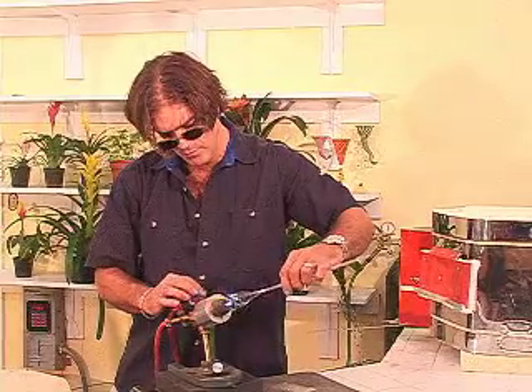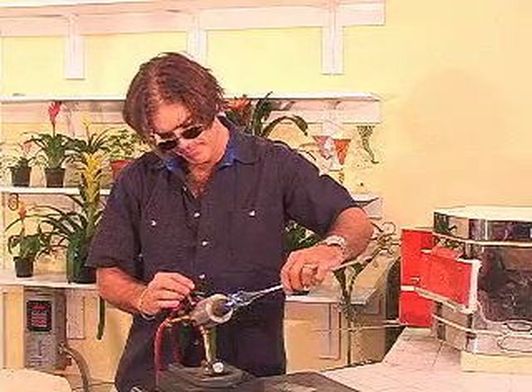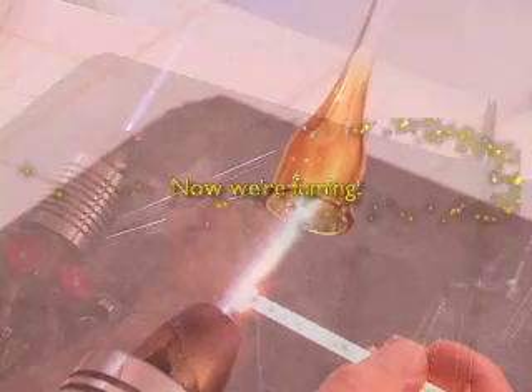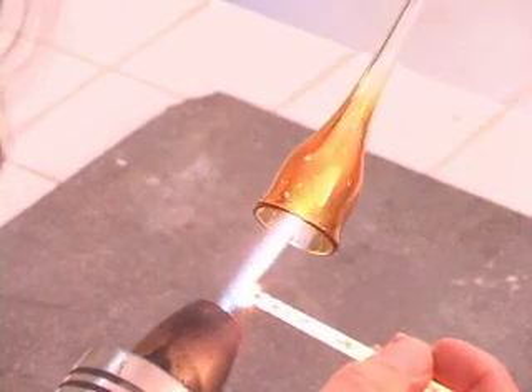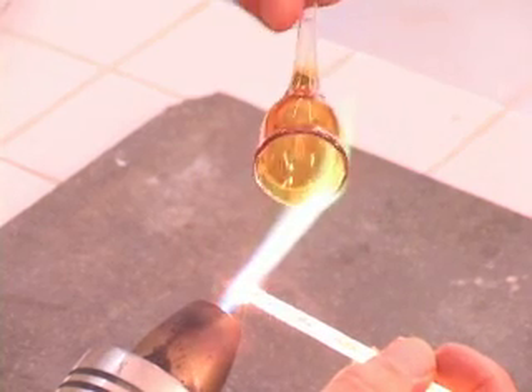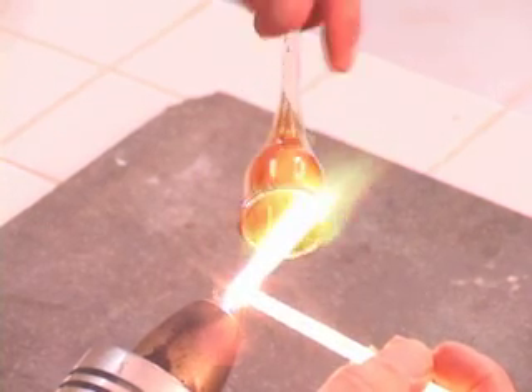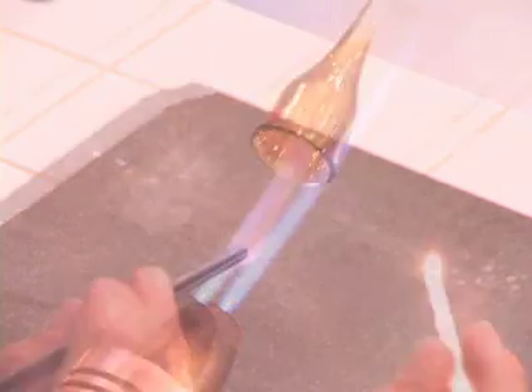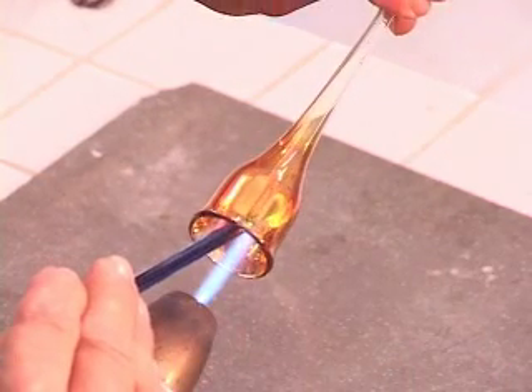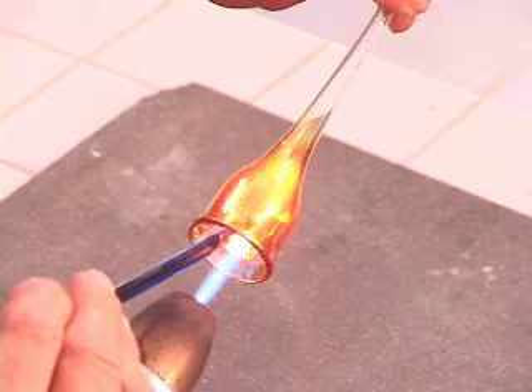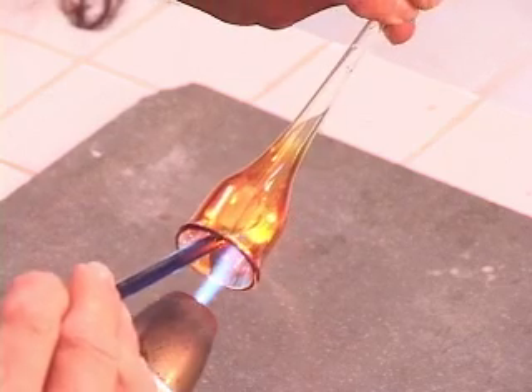With a neutral to slightly oxidizing flame, bring the silver into the bottom part of the flame. Hold your tubing 2 inches from the silver and rotate your tubing while bouncing the silver in and out of the flame. The vaporized silver will deposit on the inside wall of your tubing. Do the same with the gold.